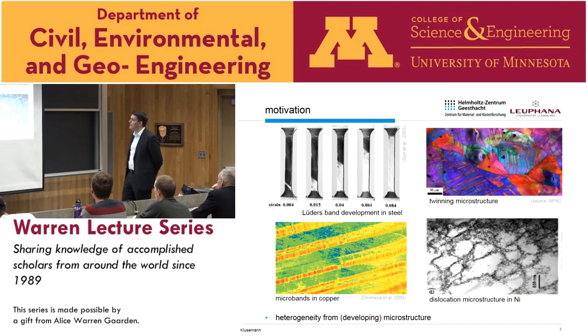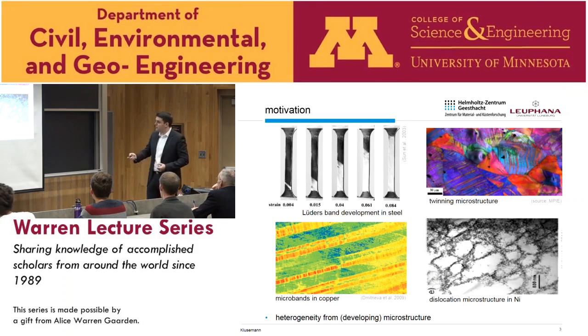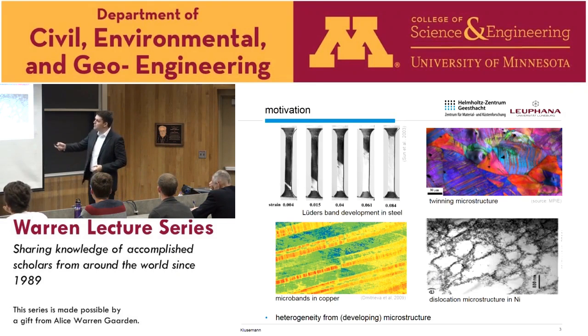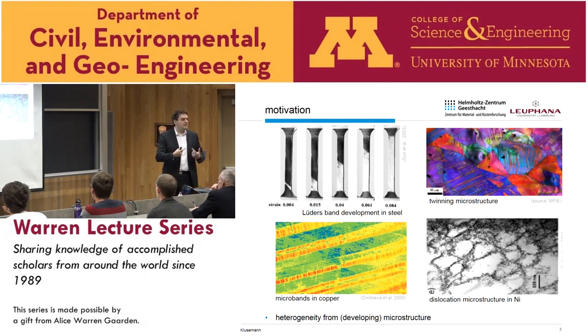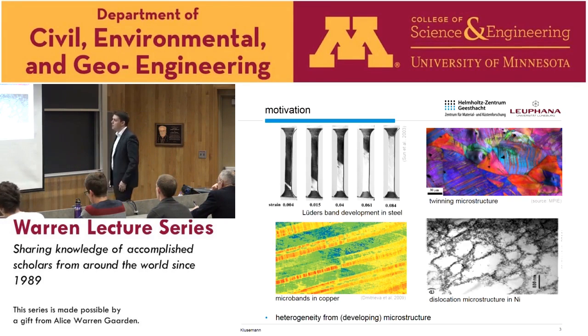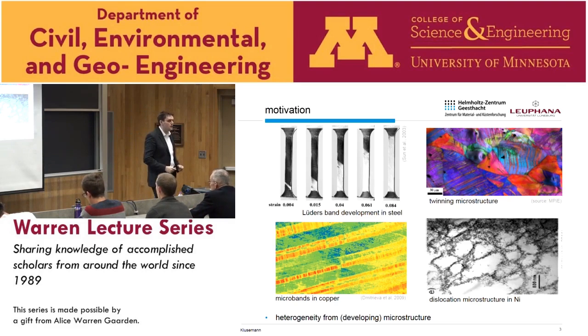Another example is here, for example, a twinning microstructure, or here some microbands in copper, which simply means that rather than the material deforming homogeneously, you can just imagine like a tensile test, you pull on it, and you would expect everything is deforming in a similar way. Now, in this material, it happens that you have these microbands, which implies regions of high and low plastic strain, which is energetically more favorable rather than having a homogeneous distribution. And I think this example probably everybody knows is the dislocation microstructure in nickel. So rather than having also a homogeneous distribution of these dislocations, you see this very typical dislocation cell structure.